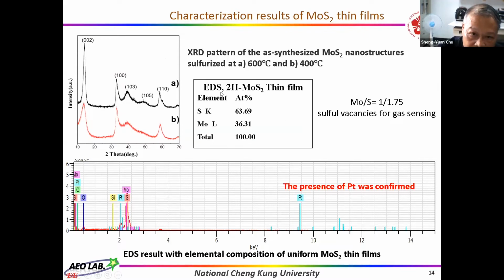However, from the EDS data, we can see the Mo to sulfur ratio is 1 to 1.75, which means there are sulfur vacancies. And this sulfur vacancy is very useful for gas sensing. Also, from the EDS data, we can see the Pt electrode signal was confirmed.